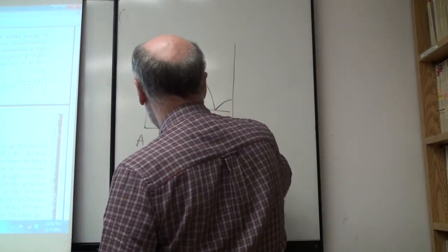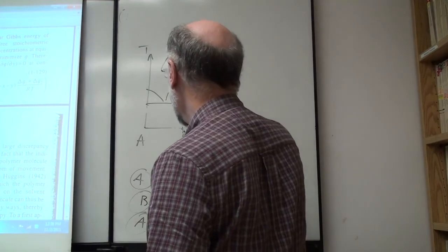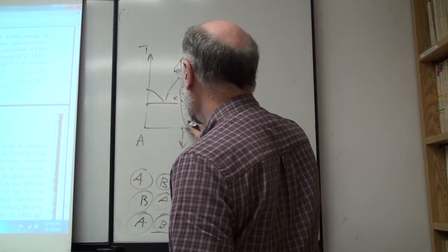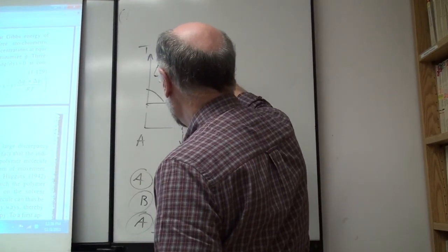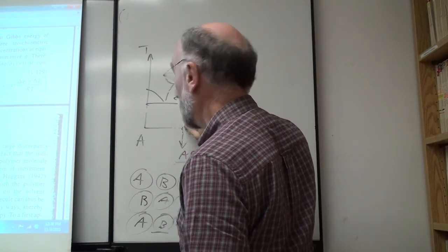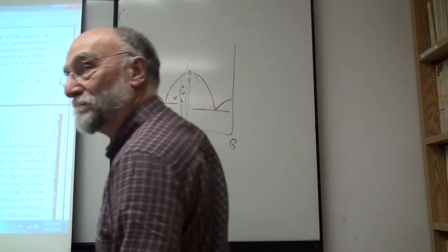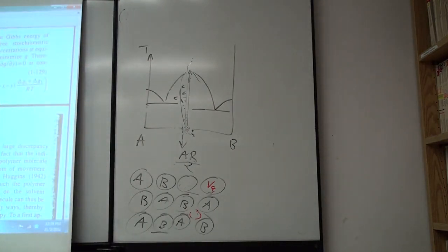But yes, measured at 50%, the enthalpies at 298 are a very big thing, because if you have the enthalpy at 298, the melting point basically gives you the Gibbs energy, equal to the Gibbs energy of the liquid, so you can work back to get the entropy. Enthalpies give you a lot of information. And they're also not that hard to measure. You usually find them in the literature. In the liquid state, the phase diagram gives you the Gibbs energy, but it doesn't give you the H and the S. So if you can get enthalpy of mixing values in the liquid, that makes life a lot nicer.